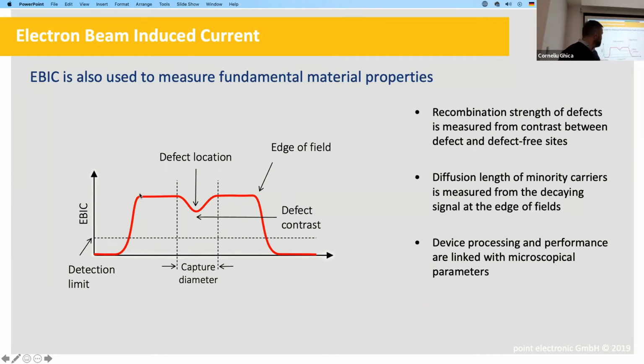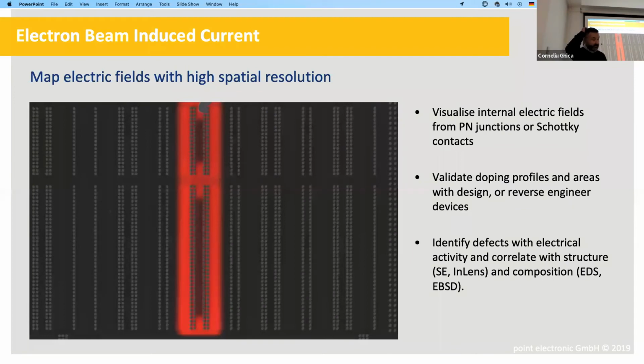We can also see from the edges of these fields, we can pick up information on diffusion because all this profile is diffusion driven, and this is diffusion of minority carriers. So we can measure with high spatial resolution the diffusion length of minority carriers. So it's quite a powerful technique, and it's been developed very extensively, and it's been used very heavily. I'm only going to scratch the surface a little bit.